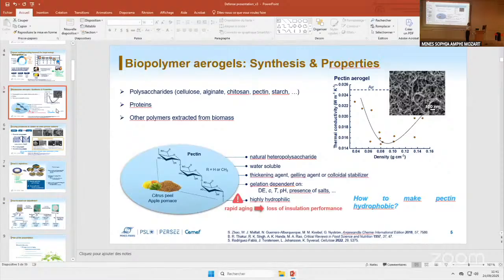I mean, my comment is more that if you do compression, yes, it's maybe logical that you can go to higher density. With cellulose, there is also strong alignment of the nanofibers upon compression, which is just a physical effect. If you compress uniaxially, you will align the fibers. So it is a very attractive approach, but of course not very tested, practically feasible. Good.